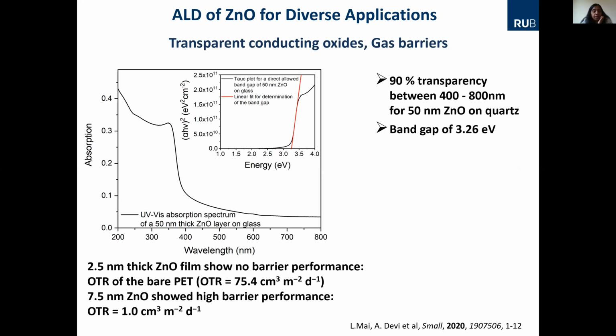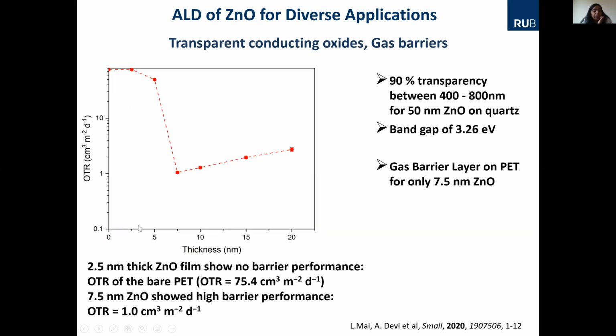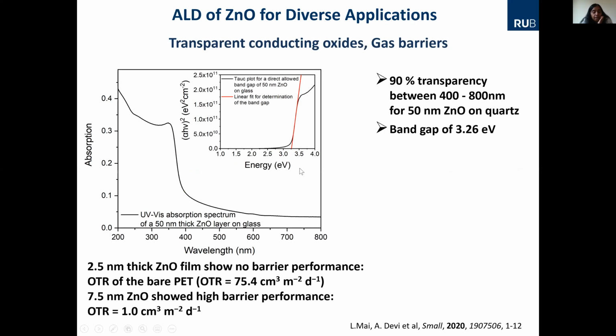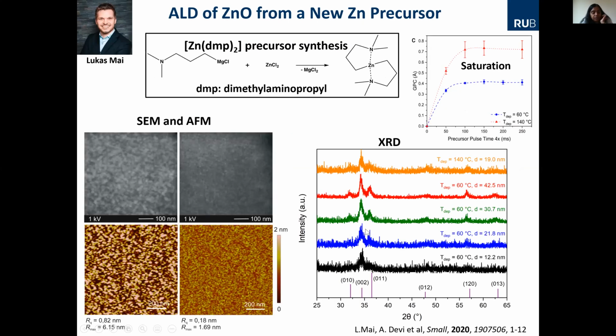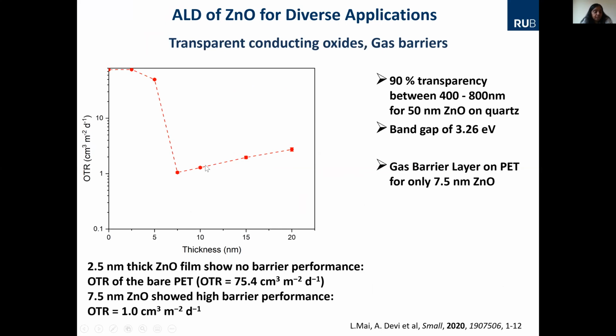And then the other application we went to is, okay, what about the gas barrier? Because this is also an interesting material. We found that for a film around 7.5 nanometers, we had a good OTR. Above that, it increases. That is because, maybe you can recall, as the deposition temperature increases, the crystallinity increases. That means there are pores or there are grain boundaries, and that is why the water or the oxygen